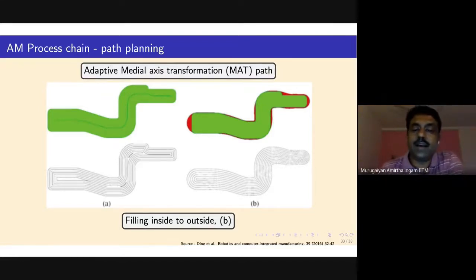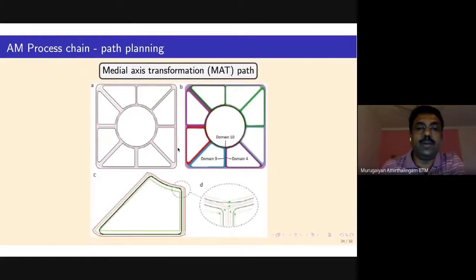So this is the state of the art right now in path planning, where we can generate a defect-free component in a DED process, or even any other process which requires good dimensional accuracy. One example of using the medial axis transformation path is generating a reinforced panel for an aircraft fuselage. First we have the geometry and the medial axis identified, and then we follow the medial axis from inside to outside to fill the entire layer. This is right now used in most DED-based processes to achieve good dimensional accuracy.